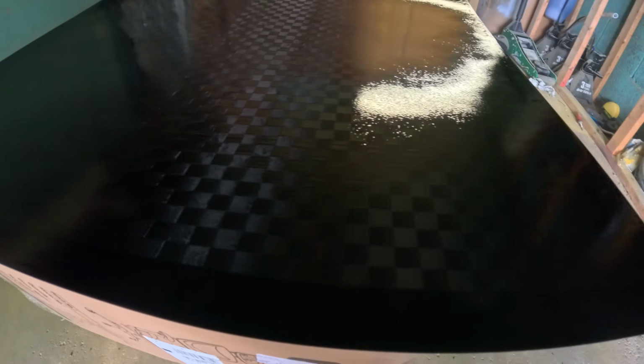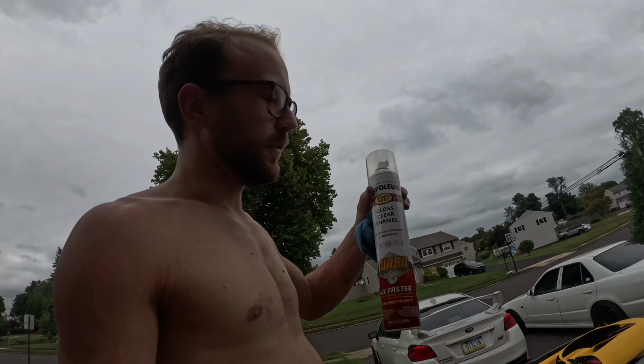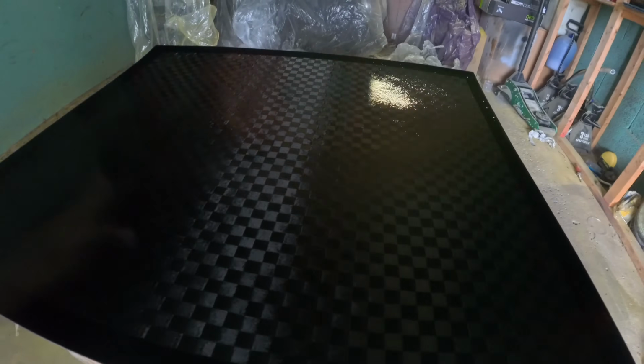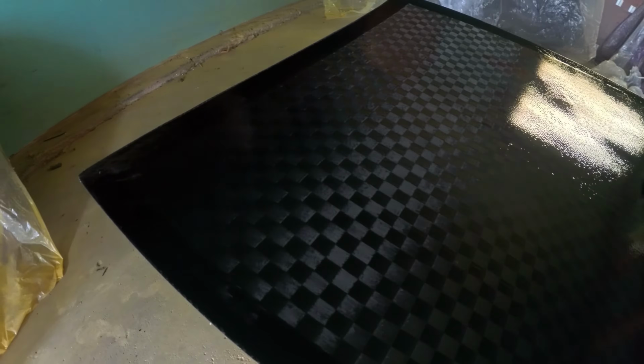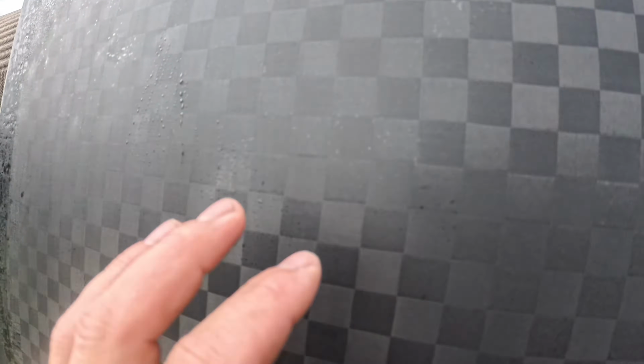which will serve as our headliner, with a thick layer of Rust-Oleum TurboCan gloss clear. After allowing the clear coat to dry overnight, it was ready to be wet sanded up to 2000 grit to remove any orange peel. If you still see spots that haven't been sanded to a matte finish, you need to keep sanding. Just make sure you don't sand into your carbon layer. Now that all the orange peel is removed and the panel is sanded up to 2000 grit, you can hit it with Adam's 2-step compound and polish with the orbital polisher and get this thing looking like glass.